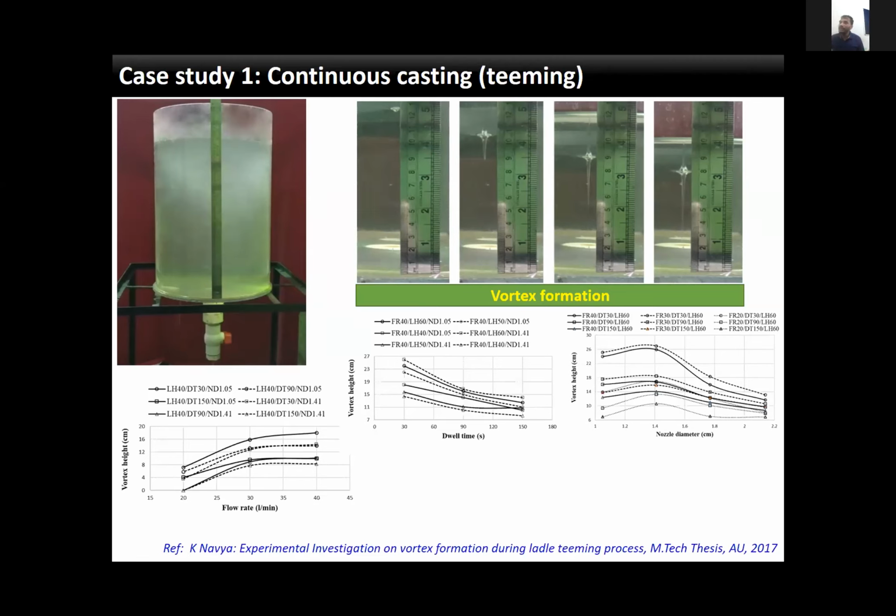So what is it basically simulating? It is simulating the motions present in the liquid steel in your industry due to turret rotation, lifting of the ladle, and purging of the liquid steel with argon. All this sets up some amount of residual velocity in the liquid steel in the industry, which is being simulated by using an initial filling flow rate of water.